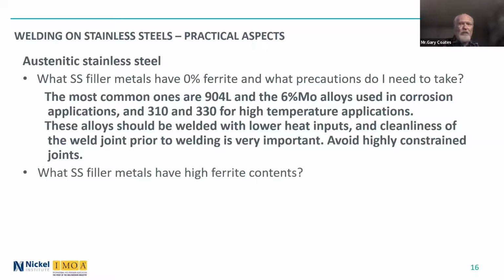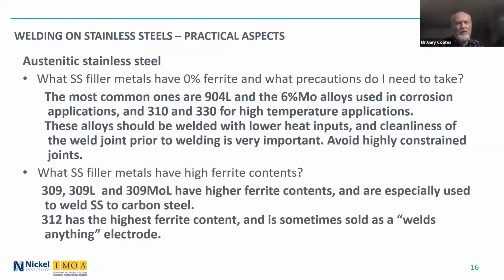And what stainless steel filler metals have high ferrite contents? Well, 309L, 309, and a variation of that called 309MoL. They have higher ferrite contents than 308L and 316L, and they're especially used to weld carbon steel to stainless steel. Carbon steel can contain contaminants such as a higher sulfur content that can lead to hot cracking, but also you have a thermal expansion mismatch between the two, so you have a more highly stressed joint there.